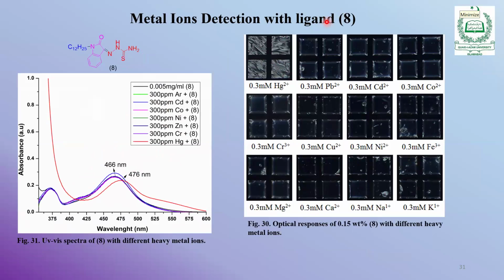With the second amphiphilic ligand, again the same testing was done. And here also we see that the mercury ions introduction in the liquid crystal sensor gave you bright texture, and in the UV it gave you a shift of the band from 466 to a maximum of 476 nanometers. So these changes, they show that some of the things are going to happen with the mercury and your ligand.